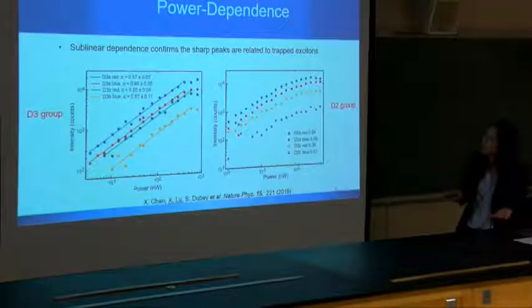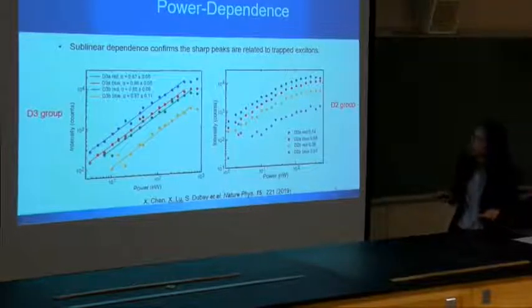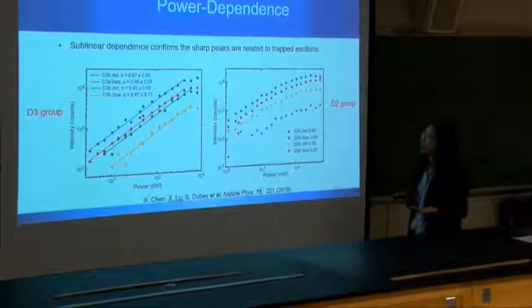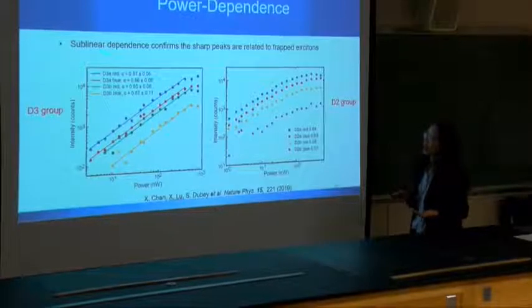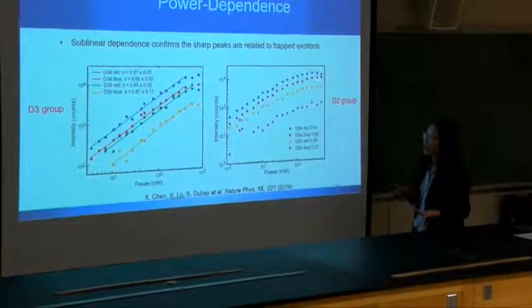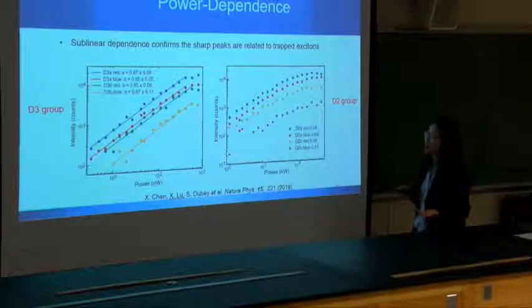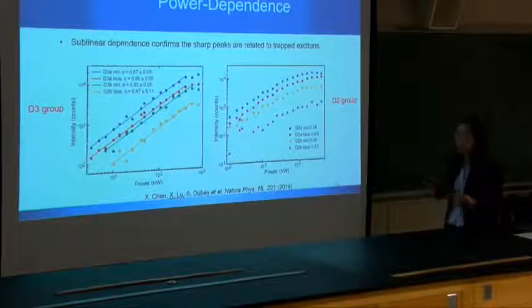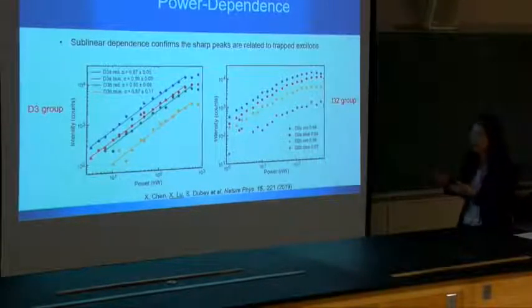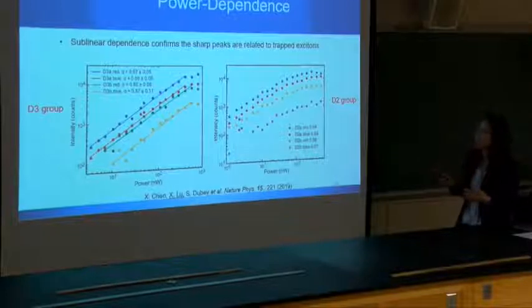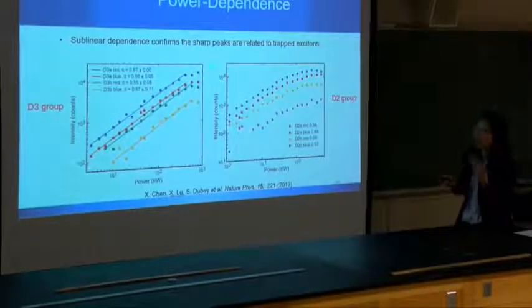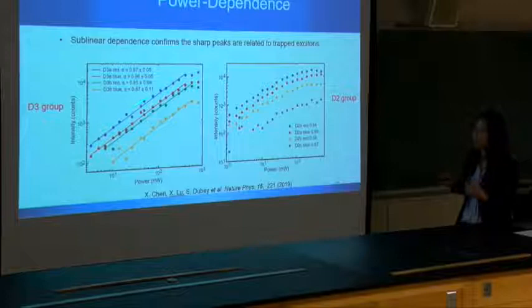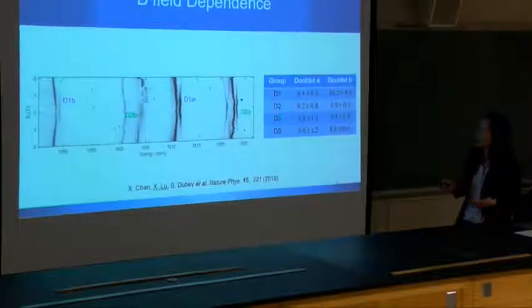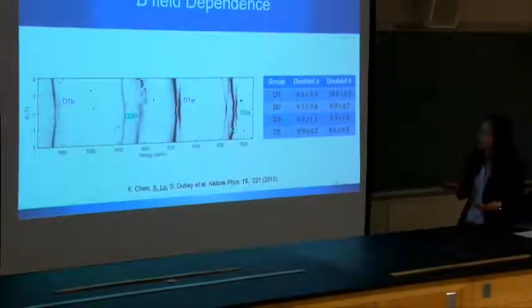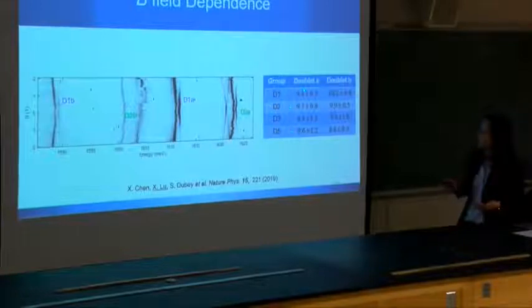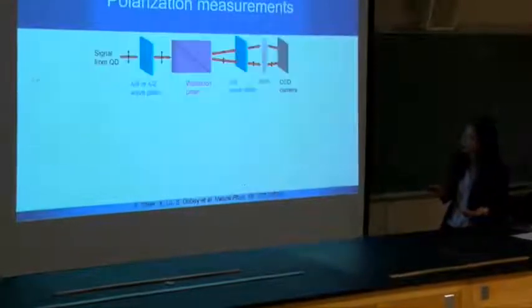And here we perform power-dependent measurement. We found that the parent peak and the phonon replica exhibit the same slope. This is very important, as if they exhibited different slopes, that could indicate different species. So this further confirms they are a phonon replica related to the same emitter. And this is from B-field measurement. We found the g-factor is also the same.